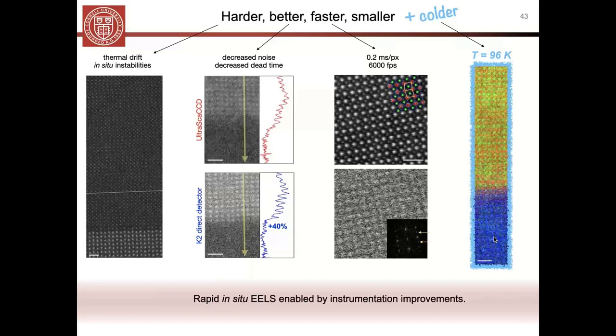So okay, do you really need the very high resolution and structural precision when you do EELS across larger length scales? So why not use the STEM images to extract high resolution structure and the EELS to survey electronic states across the regions? Yeah, I think that's how we do it now, but there's always this question of if you have to correlate some kind of average electronic measurement back to the area you think had this sort of structure going on, there's always these questions about, well, did that signal come exactly from that area, and how sure are you, and did we accidentally average over something that we didn't want to see, right?